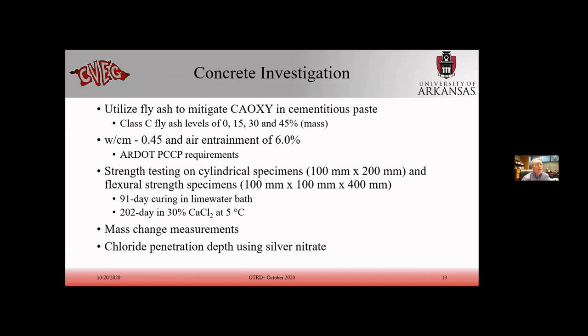We followed our standard ARDOT requirements. We made 4x8 inch cylinders, and then 4x4, about 400 millimeter MOR specimens. We cured in a 91-day cure in a lime bath. The 202 is kind of a screwy number because the COVID affected us.